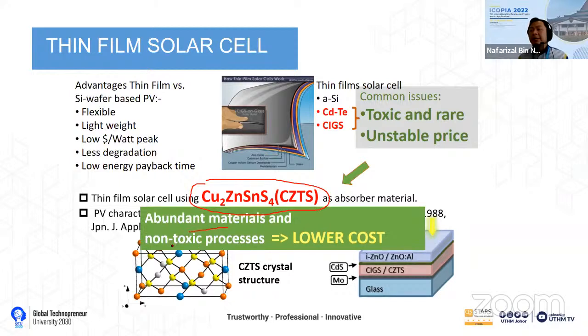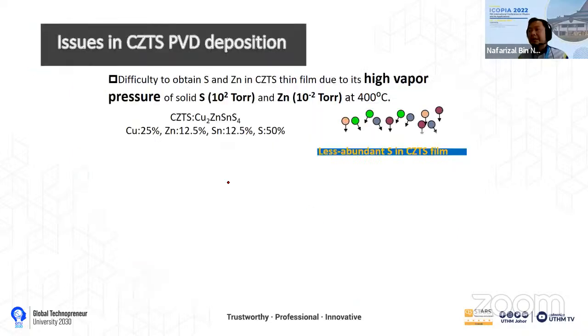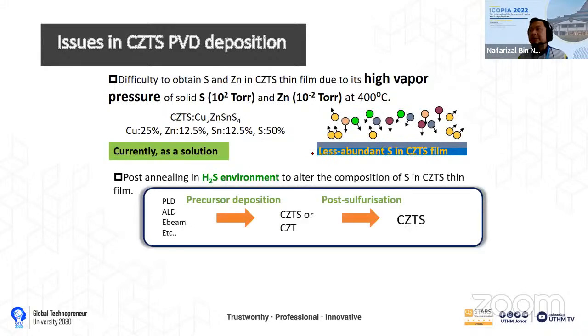It is an abundant, non-toxic process, so we propose, you can see that this is at lower cost. But the issue in this CZTS material is the low abundance of S in the thin film, because sulfur is a highly volatile material. So when you put it inside a vacuum chamber, it's easy to vaporize. So that is the issue. That's why we think that we need to understand how the sulfur can go into the thin film.